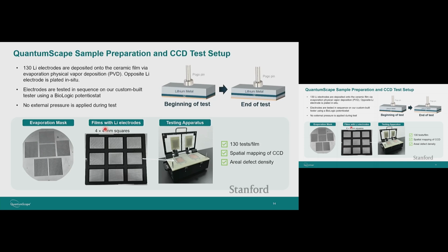To collect more data in series, what we do is we take one separator material and then deposit a lot of different electrodes on it so that we can test as a function of the area. We can get a statistically relevant sampling all in one shot. And then we've also done a lot of optimization to make this a really fast turnaround test so that in about 16 hours we can collect about 1,000 data points. And we've been doing this over years at the company. So we've really collected a lot of data.